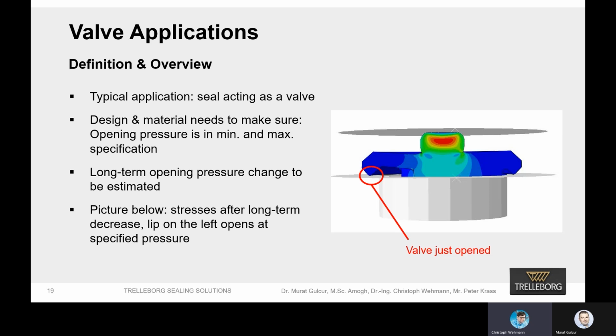So we do CSR tests and feed them into our FEA material model, as shown on the slide before. But of course, we cannot do CSR tests of 20 years. So we do them at different temperature levels, and then we use time-temperature shifts to capture the behavior long term. We have to do tests at elevated temperatures, and then we can use the shift model to create a material model which is valid for a long time period, so approximately 20 years.